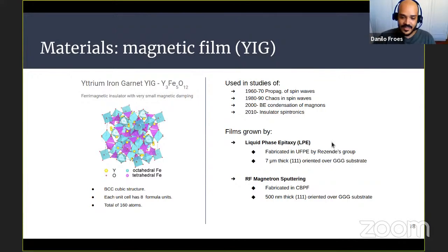So we have YIG samples made by liquid phase epitaxy. They're 7 micrometers thick, 111 oriented. They were fabricated by Sergio's group. We do not fabricate them, so we have very few samples of those, actually just 2 samples, so we could not get it wrong. So in order to do some testing, in order to do some experiments with more time, we actually used our self-fabricated films from magnetron sputtering. They were in the order of 500 nanometers thick.